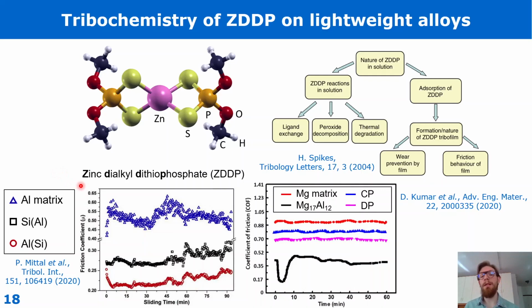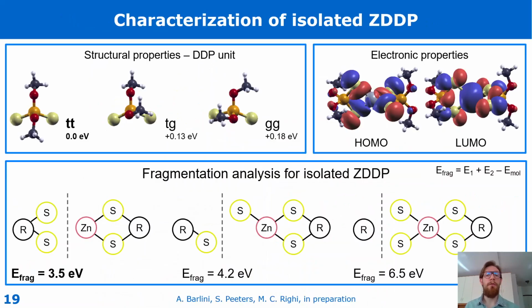So as you can see from these two studies, ZDDP is not able to provide low friction in all cases. So here you can see there is high friction when ZDDP is used on an aluminum matrix, while it is able to provide low friction when the tribological tip passes before on silicon and then on aluminum. On the right you have a similar example. In red you can see the friction coefficient when ZDDP is used on a magnesium matrix. In the middle we have two aged substrates, while the black curve represents the friction coefficient on an alloy based on magnesium and aluminum.